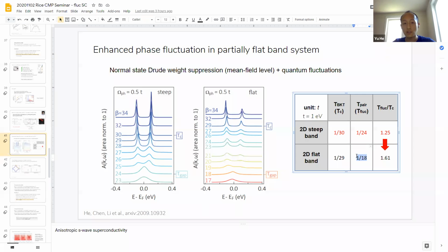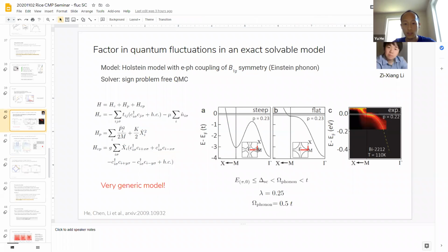So there's indeed a merit to our earlier physical intuition argument that a partially flat band in momentum space can nonetheless still enhance pairing fluctuation, especially in this case in cuprate. The pairing action predominantly happens between the antinodes. That's where the band is flat and shallow. So that's sort of our physical understanding that I skipped.